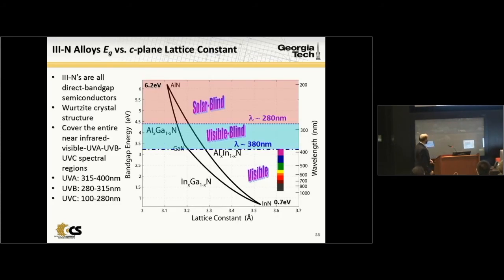This shows the details of that system that I mentioned, the quaternary indium aluminum gallium nitride system with band gap versus lattice constant. And mysteriously enough, this system covers all photon ranges from 0.7 eV, this is the band gap of germanium in the infrared, to 6.2 eV in the deep UV. And this is solar blind. There are no photons from the sun on the Earth's surface in this range.